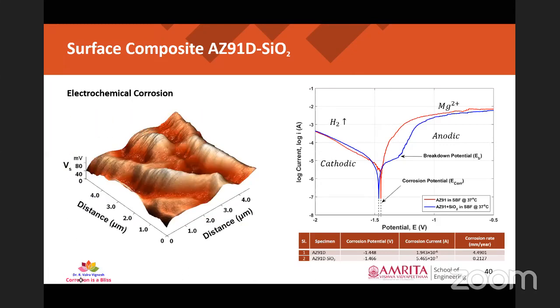So here is the result of this AFM analysis. We have done this using Kelvin probe microscopy. So the X and Y axes give us the region on which we have done the analysis, and the Z axis just gives us an idea about the surface potential of the material. We could obviously observe there is a huge difference in surface potential of the material with respect to the distance. So if we have a high surface potential, it means that the electron reactions will not take place on that region. So from this, we could literally observe that the surface of the composite, because of high surface potential characteristics, has high corrosion resistance too. Okay, yeah, fine.